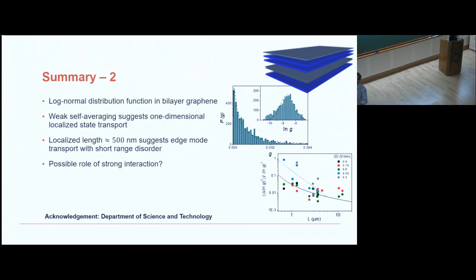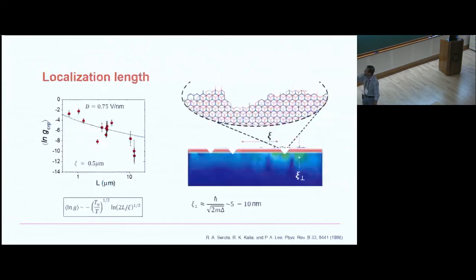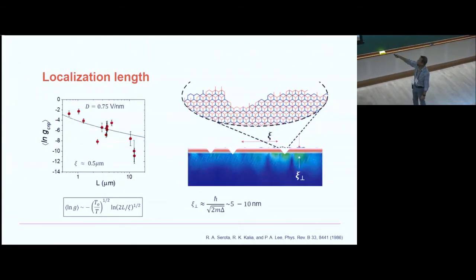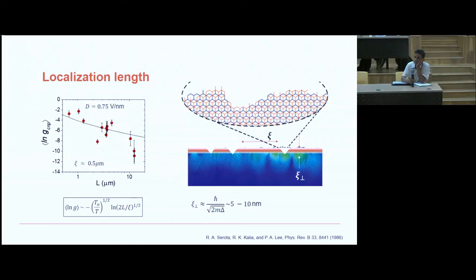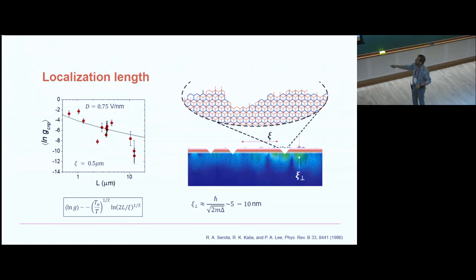So what do you mean by gap-induced localization length? I didn't understand. Okay, so essentially what you have here is strongly gapped, right? So you can calculate the width of the wave function which is going into the gap. And that is given by this simple expression, which is essentially h-bar over, and delta is the gap that I have opened up by applying a very large electric field perpendicular to the plane of bilayer graphene. So the width of the wave function in this direction cannot be more than 5 to 10 nanometers. But the localization length that I'm getting from the experimental fitting is on the order of 500 nanometers to 1 micrometer, which is about 100 times larger than this length. That means the bulk of the system cannot contribute to the electrical transport that we observe.